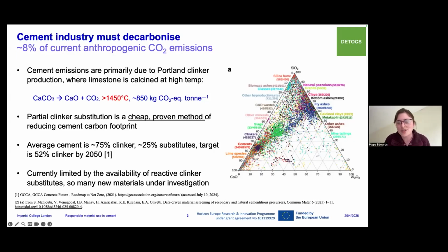So, one of the key strategies in cement decarbonisation is to lower the clinker content in cement, and it already works and we already do it. Today's cement that you'd use or buy is already blended and contains on average about 75% clinker by mass. The target for 2050 is that the average global cement needs to fall to about 52% clinker. But we want to maintain the performance and make sure that we continue making good quality, strong, durable concretes.